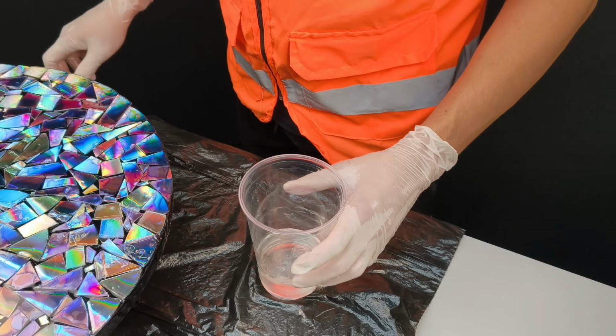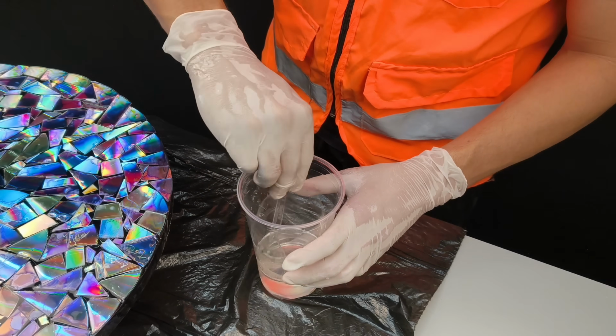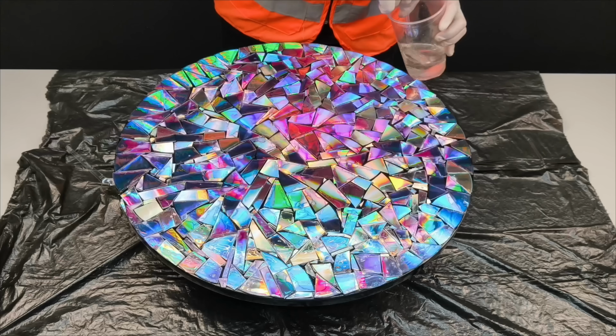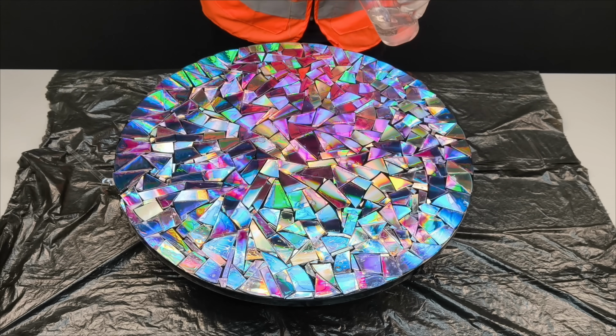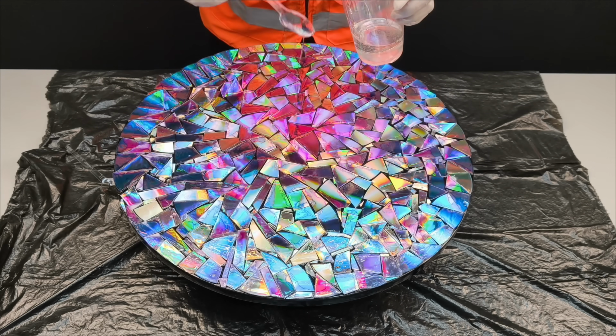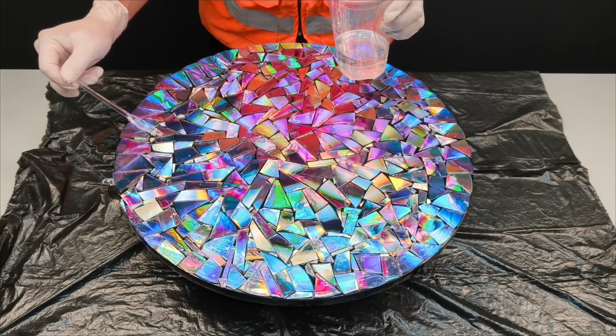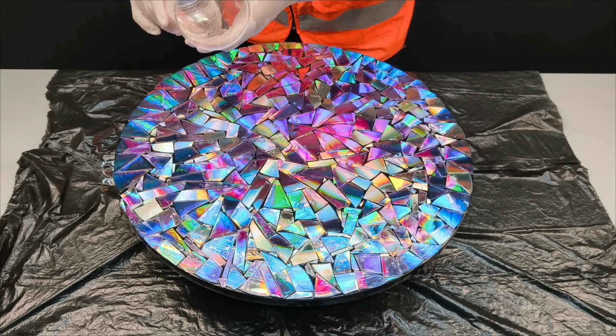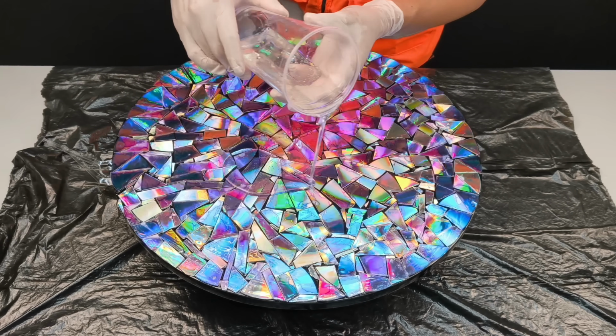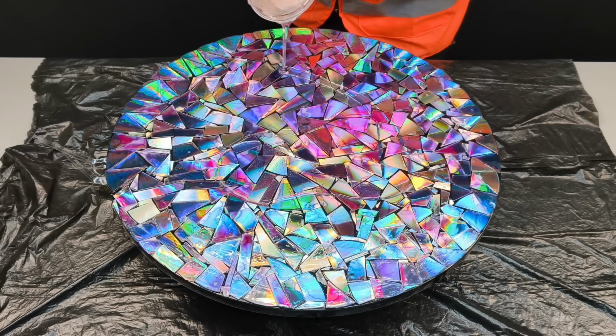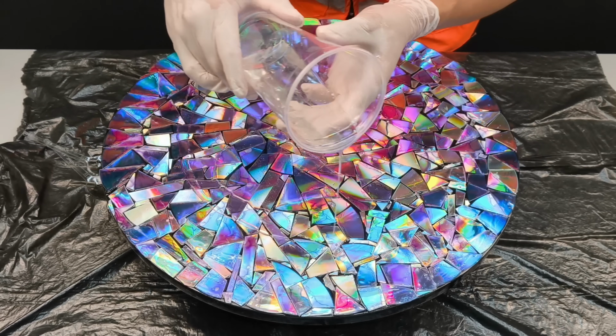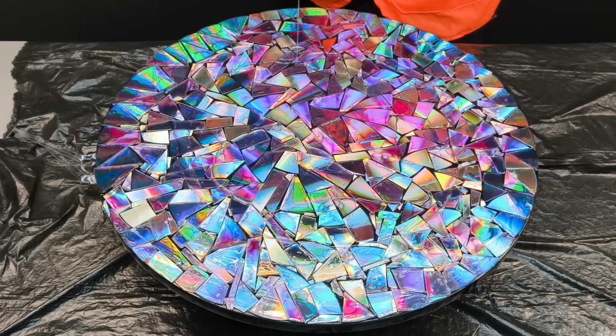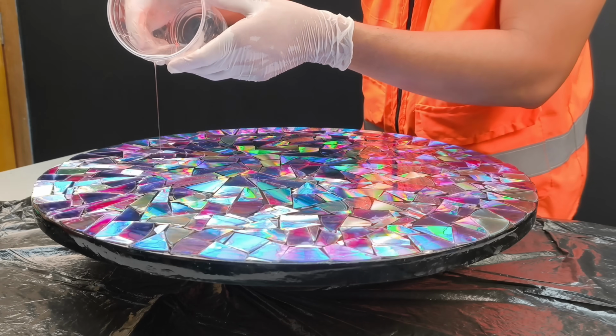The mixture is done in a controlled manner for 3 to 5 minutes, ensuring complete homogenization of the components. I scrape the bottom and sides of the container to prevent curing issues. Next, pour the entire resin onto the surface in a steady, controlled flow. Make sure the piece is perfectly level, clean, and free of dust. Also ensure proper ventilation for a smooth, defect-free finish.